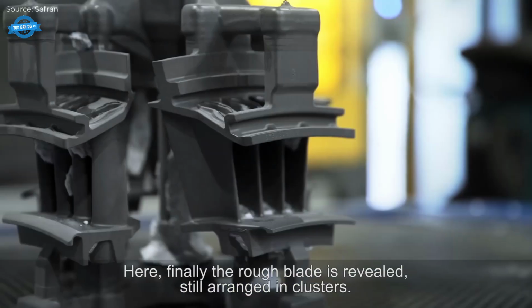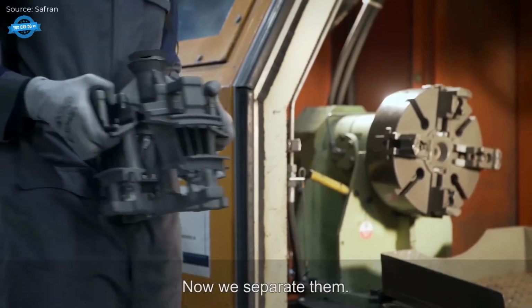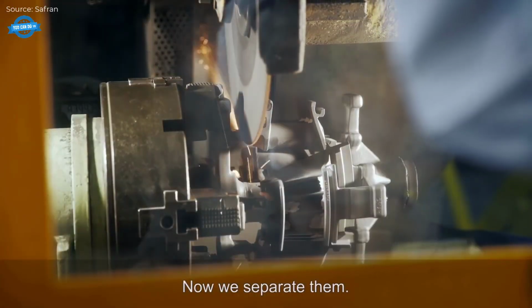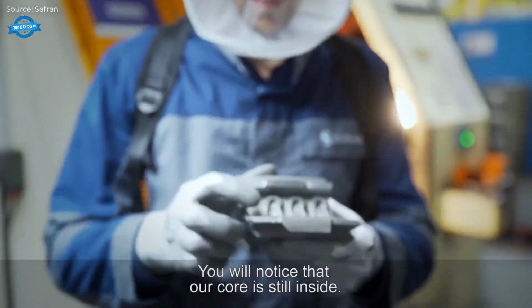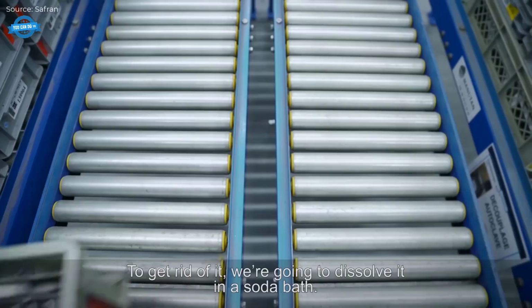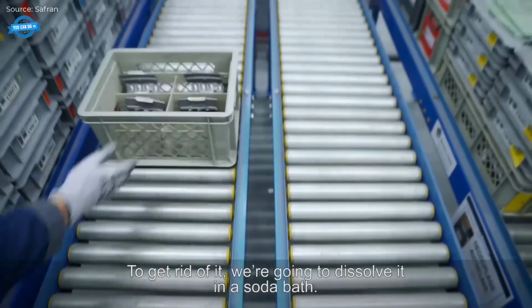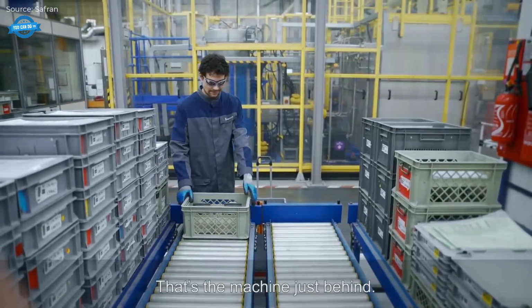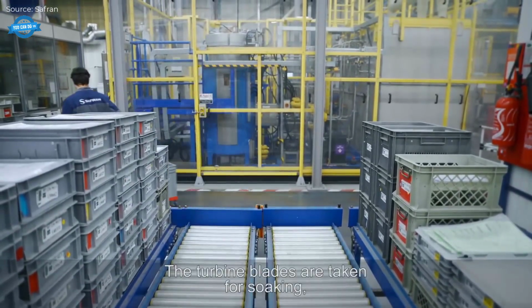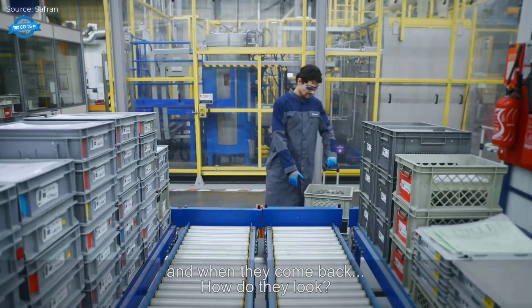After shake-off, the ceramic cores used to form the blade's internal channels are still inside. They are removed by soaking the blades in a soda bath, which dissolves the ceramic material without damaging the metal. Once cleaned, the blades move on to various finishing stages to achieve the final shape and precision.